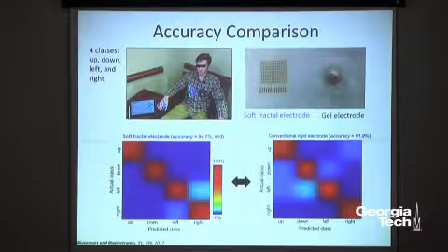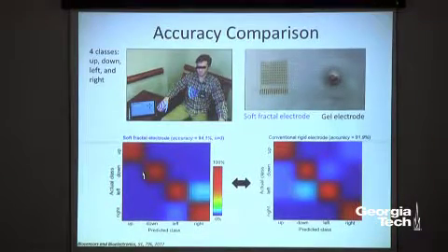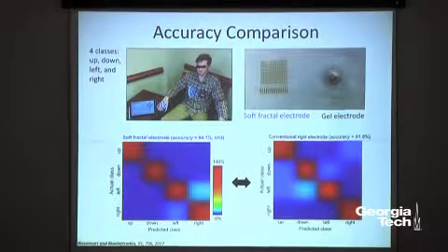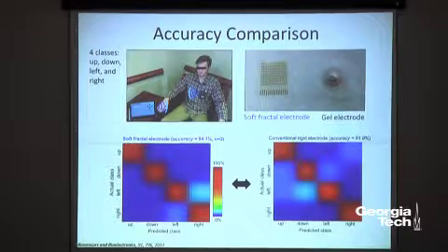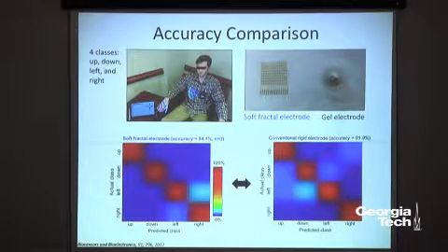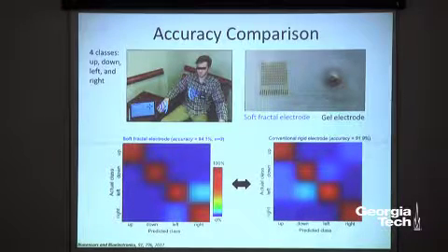So based on our test with 3 subjects, we got an average accuracy of 94% overall. So if you see this confusion matrix, which is showing the predicted class from the calculation or the actual class from the actual test, you see that up-down motions are perfect, but we have some confusion between left and right. But overall, we have 94%, which is even higher than the conventional gel, 92%. As I mentioned, we have a higher signal-to-noise ratio with better area coverage.